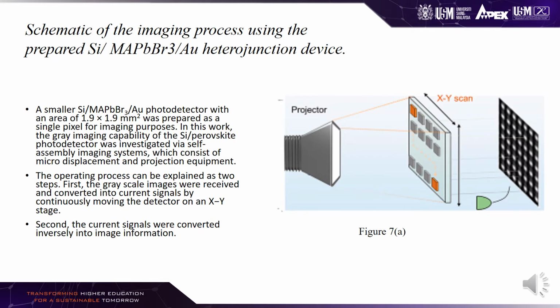This is the schematic of the imaging process using the prepared silicon MAPbBr3 gold heterojunction devices. A smaller silicon MAPbBr3 gold photodetector with an area of 1.9 times 1.9 mm square was prepared as a single pixel for imaging purposes. In this work, the gray imaging capability of the silicon perovskite photodetector was investigated via a self-assembled imaging system, which consists of micro displacement and projection equipment.